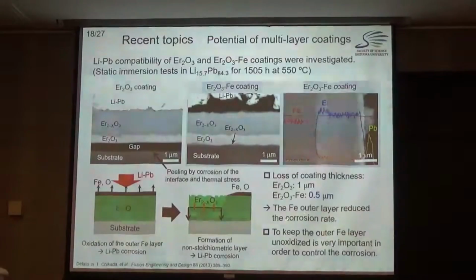This is more chemistry, not like physics. A chemical stability test of compatibility has been done. Lithium lead is a liquid breeder candidate, and it gradually corrodes erbium oxide and deteriorates the coating property. But the multi-layer structure reduces the corrosion rate. So that's very good on the engineering side. The outer layer reduces the corrosion rate.